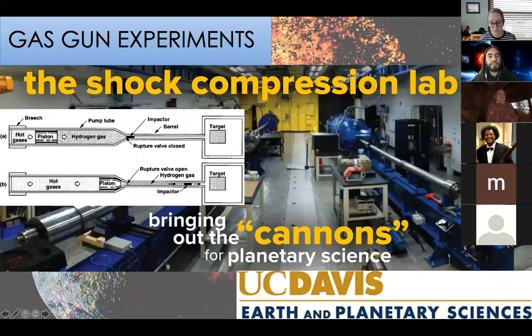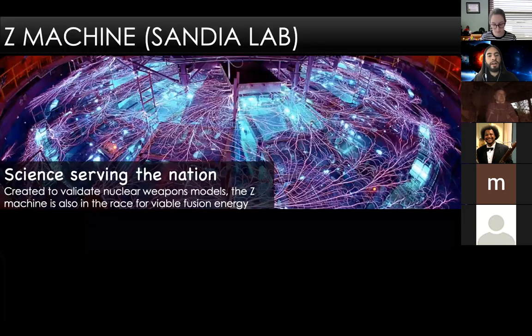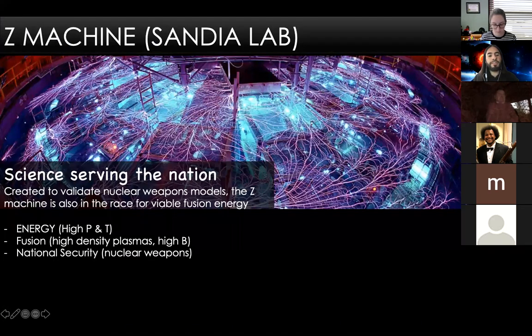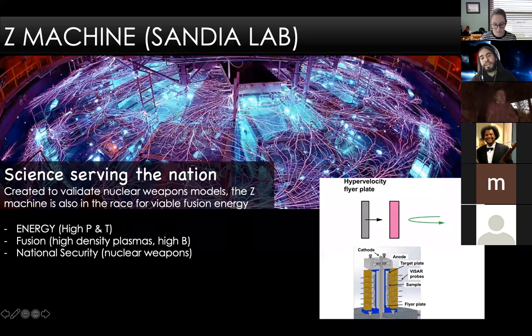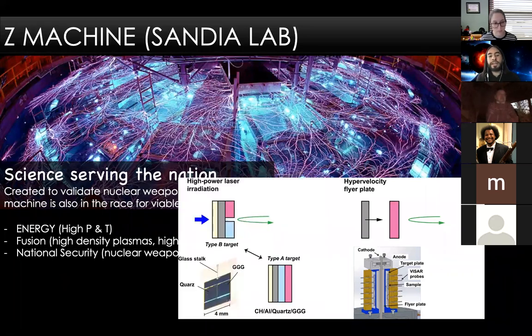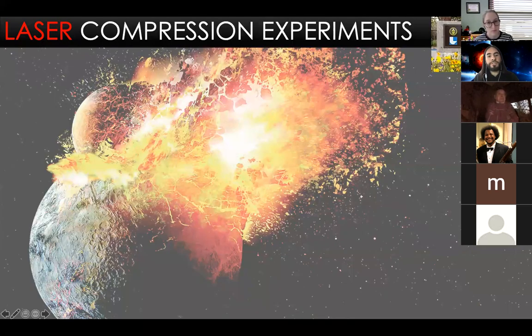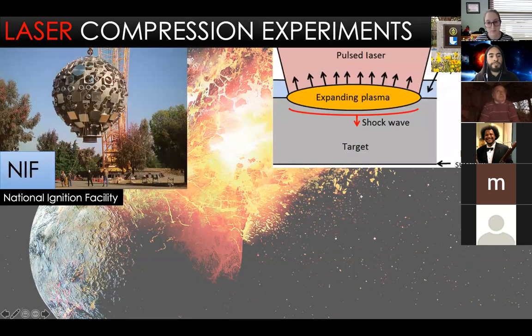So there are several labs where this has been done. For example, in UC Davis, they have a gas gun where they literally throw a bullet into a target and they generate this impact and obtain these new states of matter. You have this Z machine in Sandia Lab where they can generate extreme magnetic fields. And with those fields, they can accelerate a flyer plate that impacts a material and generates the shock wave. And you also have laser compression. And here's where Livermore comes, because in laser compression, you can actually use lasers to generate this shock wave. And that's what NIF is doing.